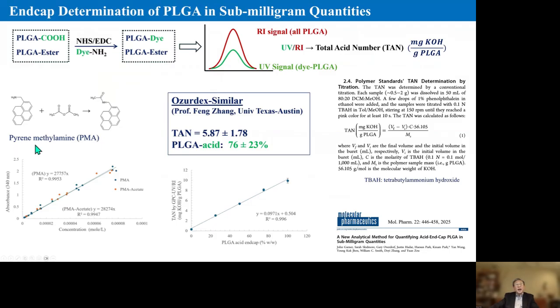So we use pyrene methylamine to modify the acid group, and then we can measure the acid signal by measuring the UV signal, and then the total amount of PLGA can be measured by refractive index. From there, we can calculate the total acid number. Now, total acid number is usually described by milligrams of potassium hydroxide, but it is not soluble in organic solvents. So we use tetrabutylammonium hydroxide and later convert it to the equivalent amount of potassium hydroxide. So that's how we calculate the total acid number.